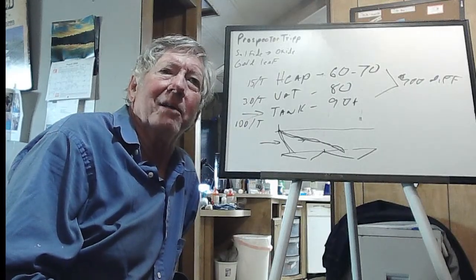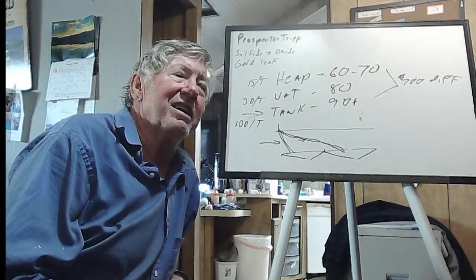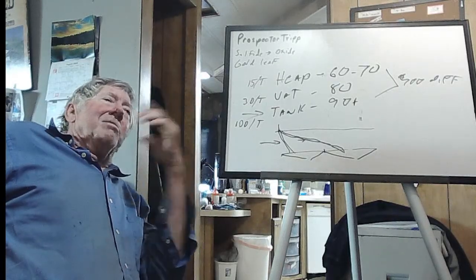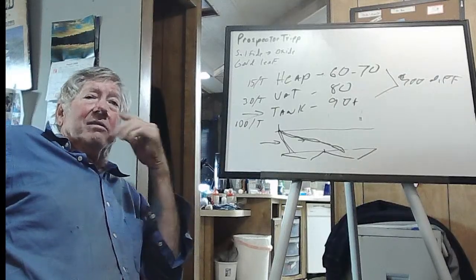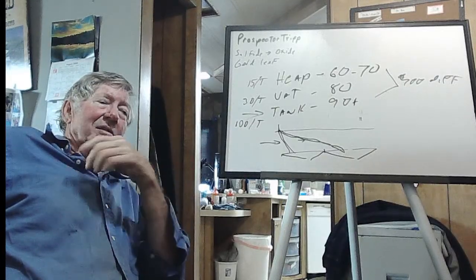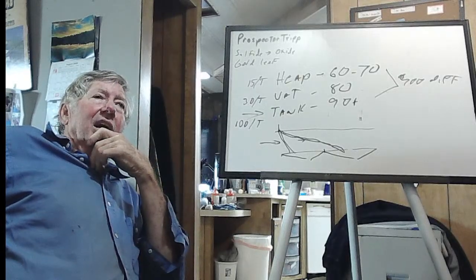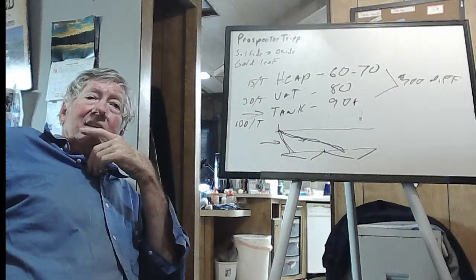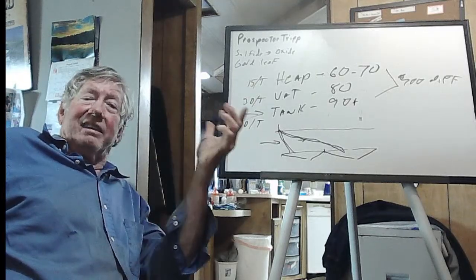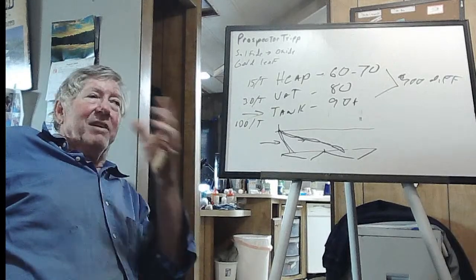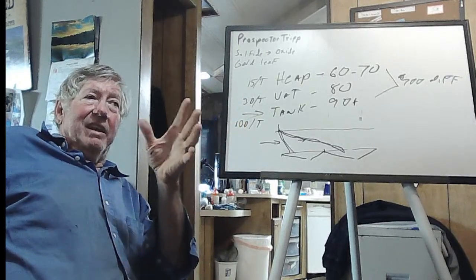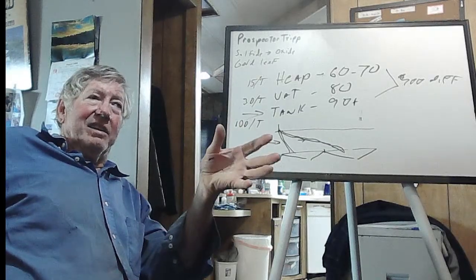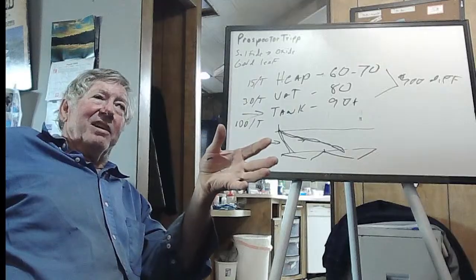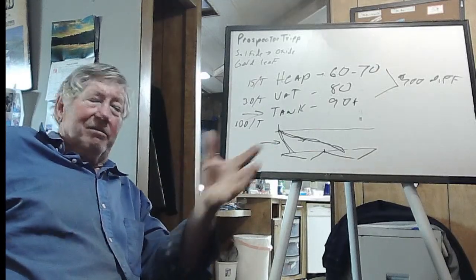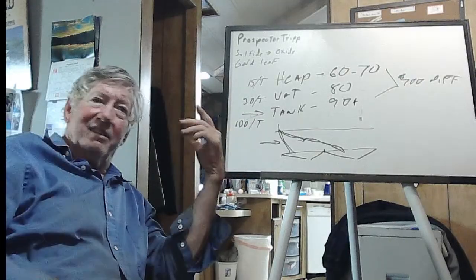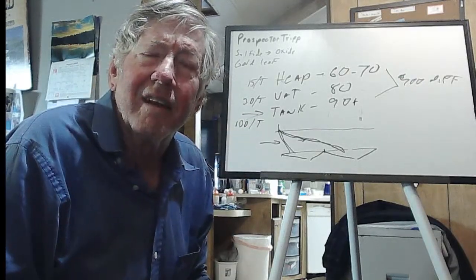Yeah, I think you're right, Brian, but that's what I'm going to be testing. And I also need to test, for example, if you have a bottle roll as your major method of dissolution of a very high grade concentrate, it would be advantageous if you can get sufficient kinetics at room temperature. I mean, if I can get 100% recovery in 3 hours at 130 degrees, but I can get 100% recovery in 12 hours at room temperature, hey, it's just rolling. Go do something else.